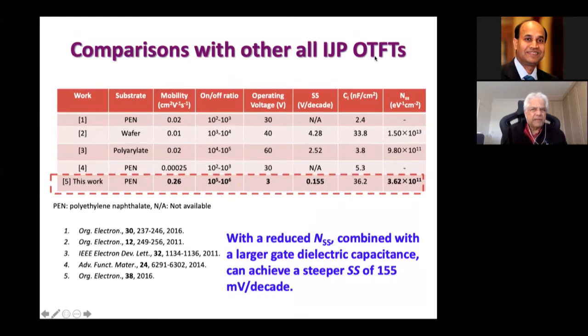So how does it compare with other inkjet printed organic transistors? Here is the interface state density, and you can see the other devices that have been reported. Some don't worry about reporting or measuring it, but certainly it's higher, close to 10 to the 12 or 10 to the 13. And with this reduced interface state density combined with a larger gate dielectric capacitance, you can achieve a quite steep subthreshold slope of 155 millivolts per decade. This number just tells you that I've got a good interface, and this is what the silicon world tries to achieve.